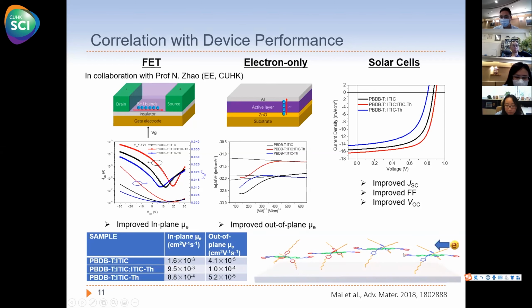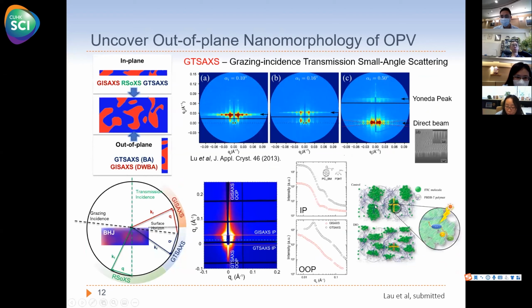improve the mobility. The second example I want to show is how we use small angle X-ray scattering to study the nanophase separation of the organic bulk heterojunction. The conventional technique can only reveal the in-plane nanophase separation. The out-of-plane structure is shadowed by the Yoneda peak, which is due to the reflection and refraction effect. So here we slightly change the experimental geometry, still using grazing incidence, but collect the transmitted scattered beam from the front edge of the thin film. We call this technique GTSAXS.